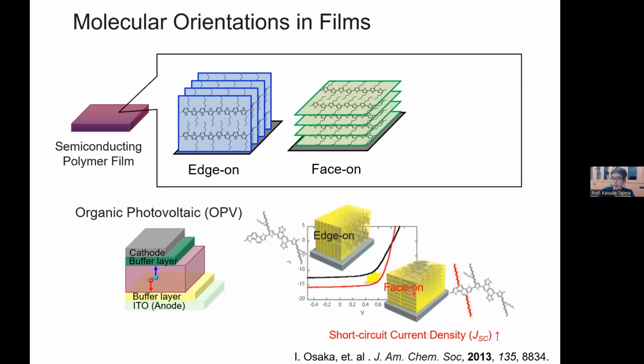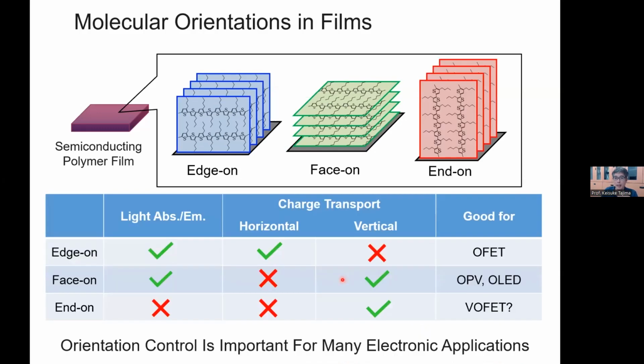And this one is demonstrated by several groups, but this particular example shows that the edge-on and face-on difference gives you this difference in the performance of the organic solar cells. And another possible orientation of the polymer chain is end-on. I'm going to talk about it later, but this one is relatively rare compared to the other orientations. But anyway, each orientation has pros and cons. For example, edge-on and face-on in terms of the light absorption are better than the end-on, because you can imagine that the light is irradiated from this side. The transition dipole moment of the polymer is in this direction, so the electric field is coupled better with these two orientations. So these are good for light absorption or light emission, but the end-on is not good.